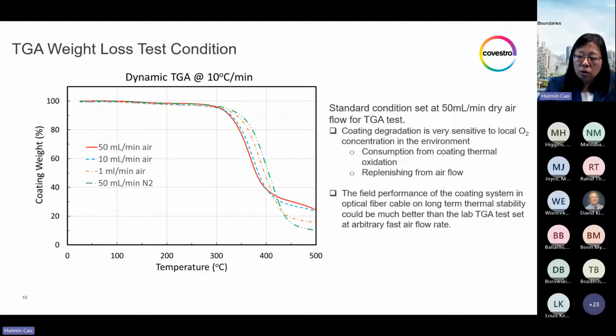So this finding could lead to an expectation that in an actual field condition, where these fibers are often in a very high fiber density cable where there is not much free space of air, and the airflow is also restricted by the cable jacket, the actual coating degradation rate in a cable structure could be much slower than predicted from these lab TGA film tests. So the purpose of this lab experiment is mainly for ranking the relative trend of thermal stability of different materials.